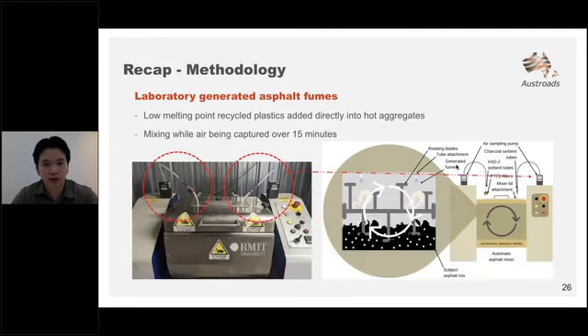And as described in the previous webinars and also in the report, the fume generation mechanism used for this study employs a temperature-controlled automatic asphalt mixer, or a pug mill, and personal air sampling pumps, as you can see circled in red, are attached to a fabricated lid that sits on top of the opening of the asphalt mixer.